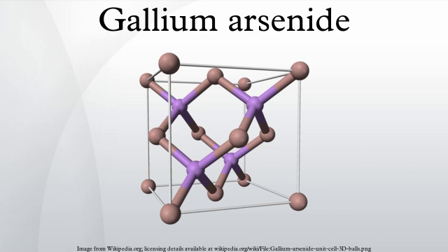Later, dual and triple junction solar cells based on GaAs with germanium and indium gallium phosphide layers were developed as the basis of a triple junction solar cell, which held a record efficiency of over 32% and can operate also with light as concentrated as 2000 suns. This kind of solar cell powers the rovers Spirit and Opportunity, which are exploring Mars' surface. Also, many solar cars utilize GaAs in solar arrays.